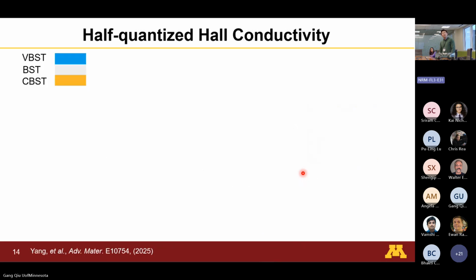All right, now, so far, everything we've done is with the perpendicular magnetic field, right? So what about we use some in-plane magnetic field? In this case, we still take the same material. We first initialize it with a perpendicular magnetic field, which drives the system into a quantum anomalous state again. Now, we remove the out-of-plane field, right? The system has PMA, so it stays in this configuration.